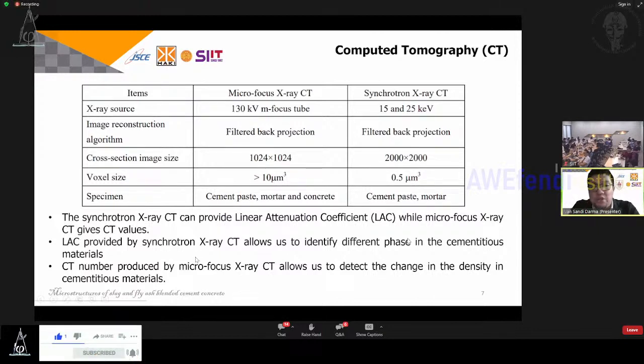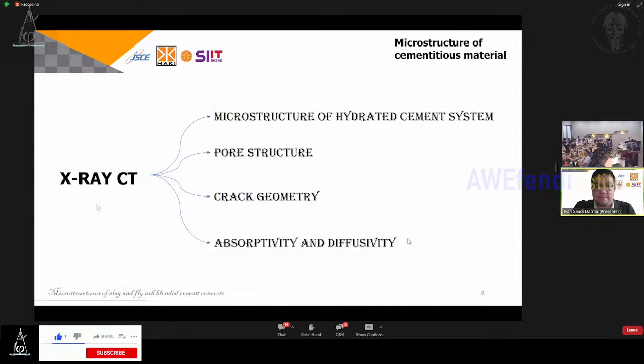So by using microfocus X-ray CT, we could find the difference, for example, before and after leaching test, before and after carbonation test, and before and after high temperature exposure. Here, I try to explore the use of X-ray CT in four types of topic. First, microstructure itself, and then pore structure, crack geometry, absorptivity, and diffusivity.